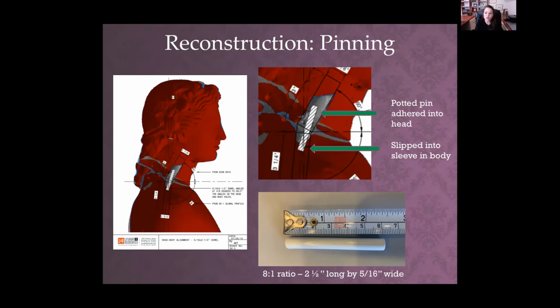And so in order to select what size pin, when the Met was working with scientists at Princeton University, they came up with this ideal ratio for a pin that holds marble pieces together, an 8:1 ratio. It's based on fracture mechanics, with the idea that the ideal pin length creates an effective mechanical connection between two marble fragments without being so long as to cause stress points on either end.